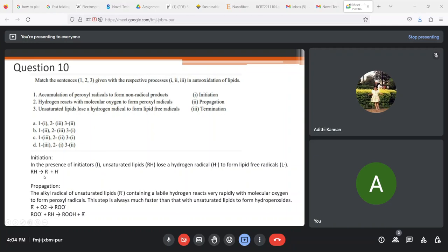So this step is much faster than its reaction with further unsaturated lipids to form hydroperoxides. So these radicals that are formed in the initiation step can either react with molecular oxygen or it can react with more unsaturated lipids. So this step is found to be faster than this step. So you can either have it reacting with oxygen, and this will further react with other unsaturated lipids, and hence you can get a chain-like reaction forming. So again you'll have an R dot. So this R dot again will react with oxygen. So this is kind of a chain reaction that is happening that will lead to a propagation of your free radicals present in your oil and other compounds. So as you can see here, the hydrogen reaction with the molecular oxygen to form peroxyl radicals is the propagation step, because your peroxyl radicals will start interacting with further unsaturated lipids and cause this chain reaction.